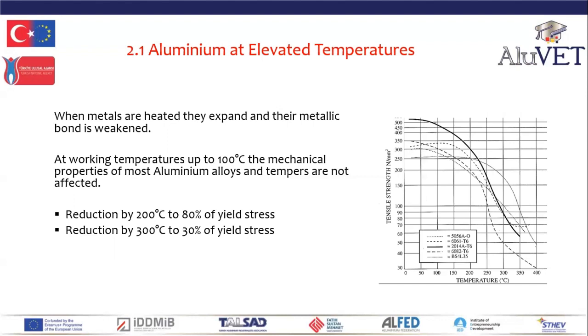So although aluminium at relatively low temperatures, 3, 4, 500 degrees C, loses its strength, it's not a problem for most applications of aluminium. So at 200 degrees C, relatively low temperature, aluminium has got about 80% of its yield strength. So at 200 degrees C, aluminium's about 80% of its room temperature strength. By the time you get to 300 degrees C, it's at a third, 30% of its yield strength.